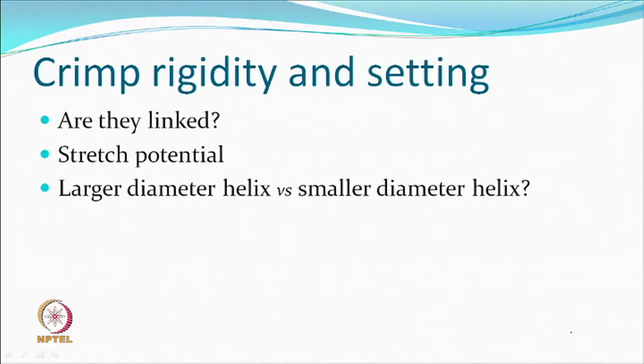Are crimp rigidity and setting linked? Yes - better setting means more crystallization and more disorientation, both favorable, which means better crimp rigidity. More setting leads to higher stretch potential, higher crimp rigidity; these three - setting, crimp rigidity, and stretch potential - are linked.